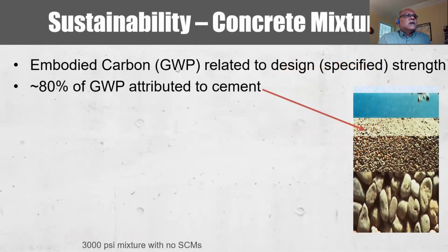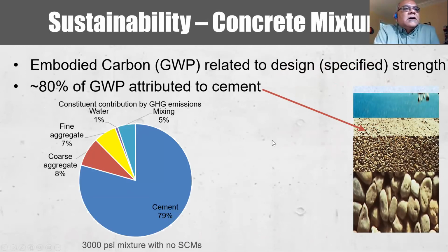Now, embodied carbon is a very hot topic nowadays, the global warming potential, and it's primarily associated with the cement content. If you look at an EPD, or environmental product declaration, you'll see about 80% of the contribution to the global warming potential comes from the cement, and that's a natural result of the manufacturing process of cement by calcining limestone and the use of fuel to manufacture cement. And so when we have goals to reduce the global warming potential, the natural approach would be to put maximum limits on cement, which is not necessarily the right way to do it because you may detract from achieving the needed performance.